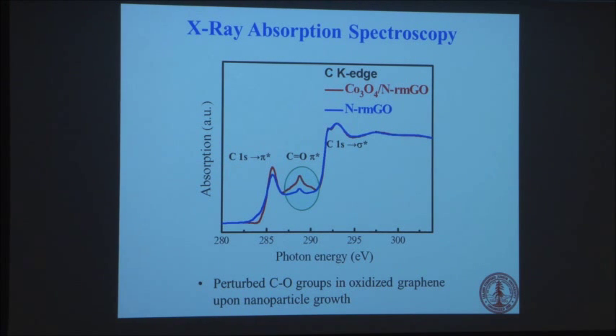Now, what evidence do I have that is strong coupling? Well, we did some X-ray absorption measurements, and this is the carbon signal. And I want to just point out in the middle here, these carbons are the carbon that's bonded to oxygen. In other words, these are oxidized carbon. And you see after you grow a nanoparticle on top, the most change we see in the spectrum is that peak. Okay, so that means that's really where this nucleation happens. Okay, these oxygen groups are grabbing the metal, and the result of that is some sort of charge redistribution, which changes that intensity. Okay, so this is a spectroscopy.